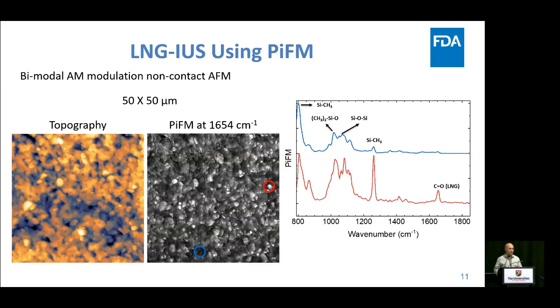And we collect a photo-induced force spectrum that correlates with FTIR. That's really fascinating because it's a completely mechanical detection, and yet it really does correlate with the optical detection. And we can identify the spectrum is a lot more rich in terms of PDMS when you're looking at it with infrared, and there's a lot of potential to really do complex excipient characterization in this case, but also identification of the sample.